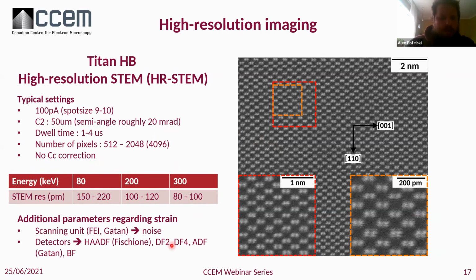So here are some typical values that you're going to get regarding the different energies and the resolution you can get. And here again, it's possible to push more. This is not technically the spec of the microscope. This is slightly worse, but these are the typical results. So usually we're going to go to 200 or 300 kV, and we're going to get something around 100 picometers. That's the case in most situations whenever you finish with the alignment.